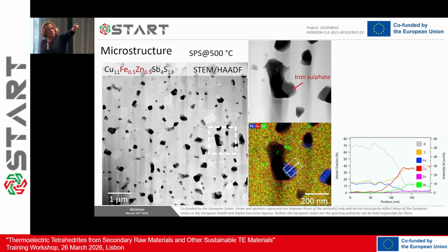What's happening is that if you have oxygen in your materials, which we always do because of ball milling—at least from the powders, from the leaks, but also from the passivation layers in the stainless steel of the milling media—this will all be incorporated in your material regardless of what you do, so we'll always have oxygen. This might actually be a good thing because we are deoxidizing the material: sulfur is removing oxygen out of the lattice, which might be good or not. We don't know.